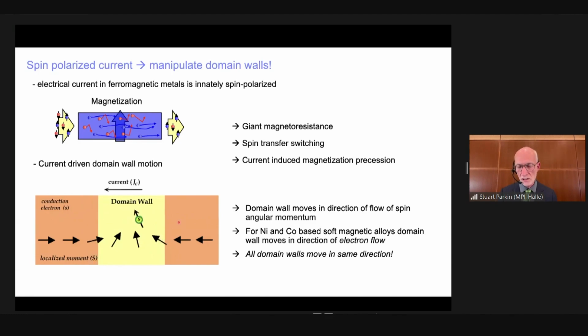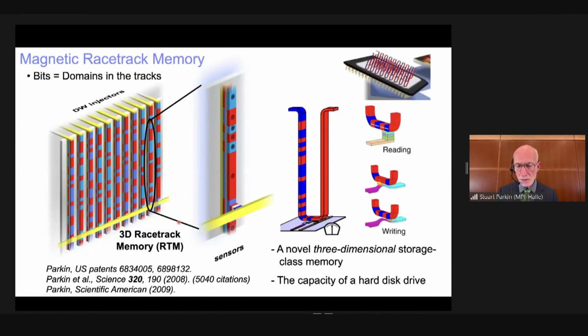Nearly 100% of the spin angular momentum carried by the spin polarized electrons can be transferred to the magnetic system. And this kind of physics allows the domain walls to be moved at speeds of about 100 meters per second. So my proposal was we could build a vertical racetrack, a magnetic wire shown in the right-hand side, where the